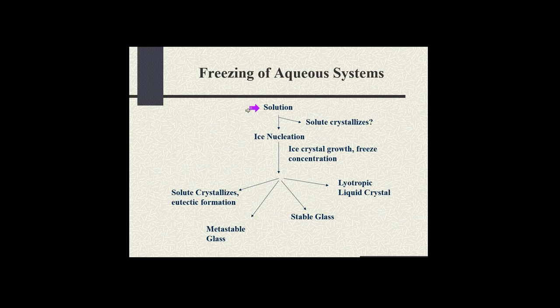Obviously, we start in solution, and as we're going down, we're decreasing the temperature. Again, as I mentioned, finally we hit a temperature where ice will nucleate, then we start to grow ice crystals. We do that at the expense of pulling the water out of the interstitial space where all the excipients and the active ingredient are located, super concentrating that phase.